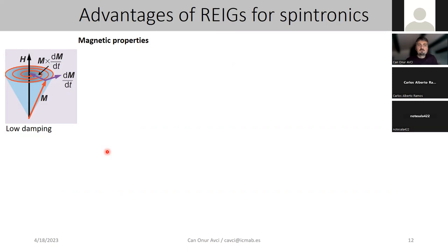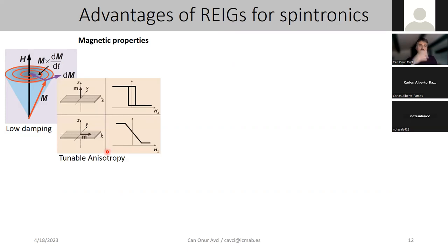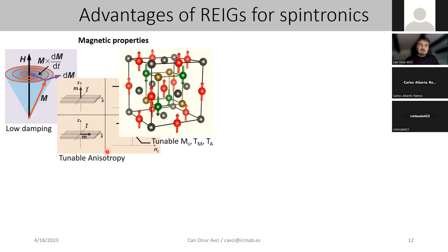For instance, for certain rare earth iron garnets, such as yttrium iron garnet, you have extremely low damping. So that is good for certain types of high frequency applications. Then the anisotropy of these garnets can be tuned, as I will explain in more detail later on. So you can make it either in-plane or out-of-plane anisotropy. Then you can also tune the saturation magnetization at a given temperature, or the magnetic compensation temperature, or also the angular momentum compensation temperature, which is TA, which can be a little bit different from the magnetic compensation temperature. And this angular momentum compensation temperature is especially important for triggering ultra-fast antiferromagnetic-like dynamics in this system.